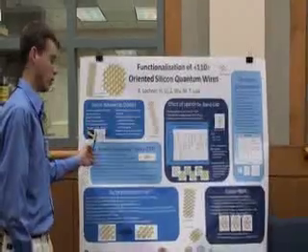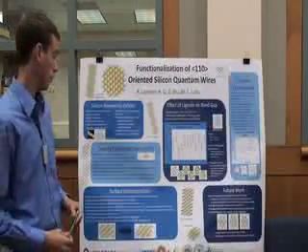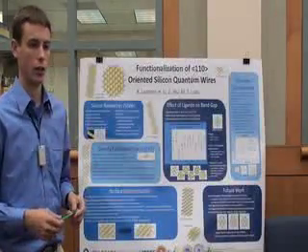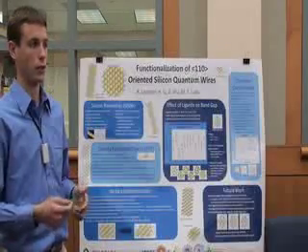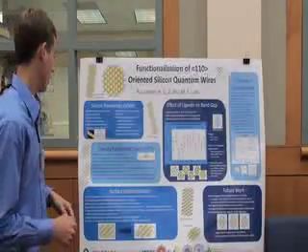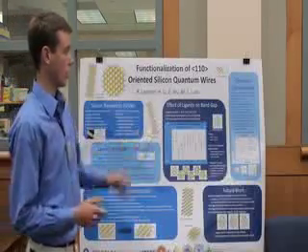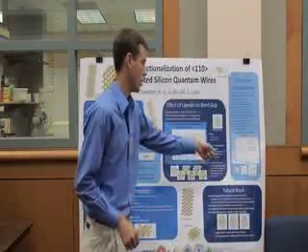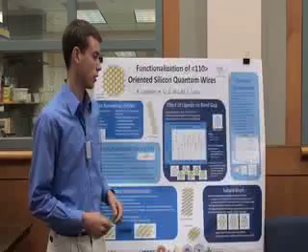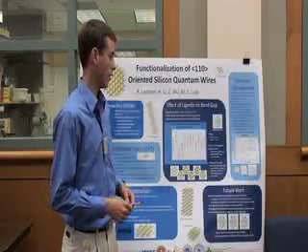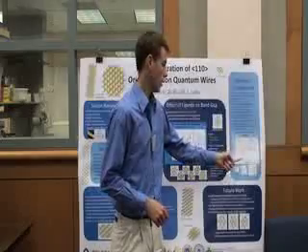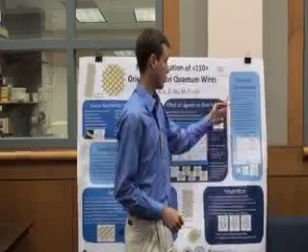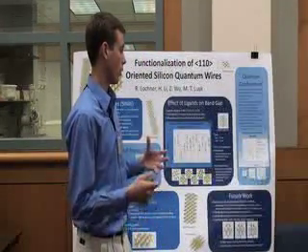I have a little summary here of density functional theory, the main point being that the ground state properties of a material can all be described as functionals of the electron density. One of the first things I did was actually reproduce some results from 2004 in which Zhao et al. showed the size dependence of silicon nanowires, and that effect is that when a nanowire is smaller, the band gap increases. That effect is because of the quantum confinement effect.